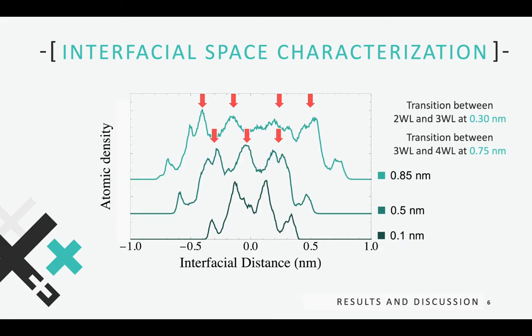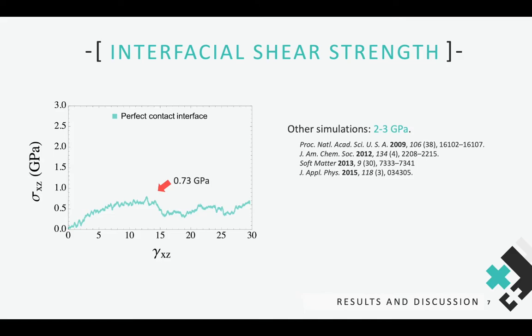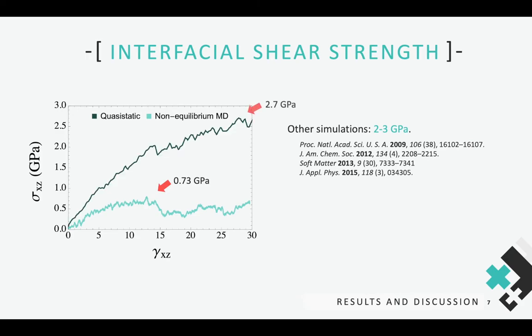We analyzed the shear strength of the simulated system and found that for the perfect contact interface, the maximum shear strength is about 0.73 GPa. This value is significantly smaller than the shear strength computed in previous works for bulk CSH, in which values were between two and three GPa. However, those literature works used quasi-static deformation schemes ignoring entropic effects, whereas our simulations were carried out at room temperature. When temperature is disregarded and a quasi-static deformation protocol is used, the predicted strength becomes 2.7 GPa for the perfect contact interface, which is in line with previous results from the literature.